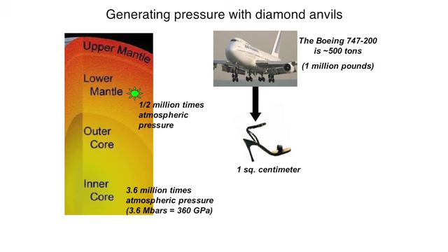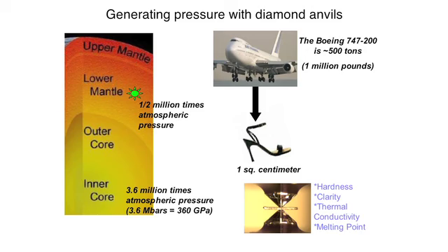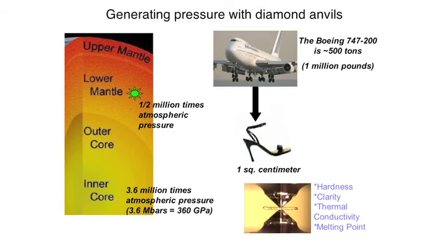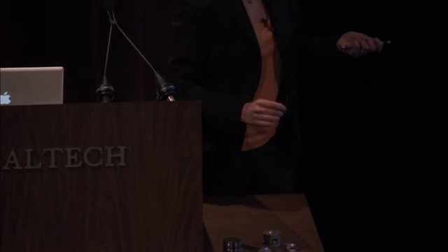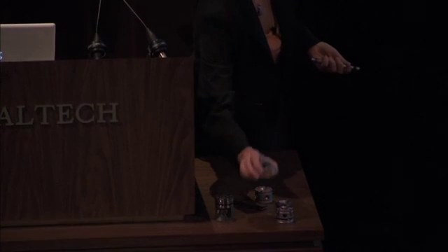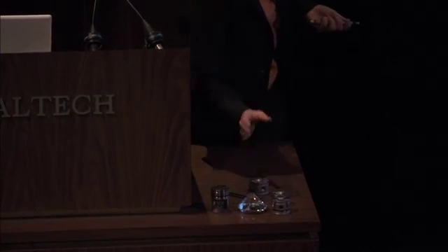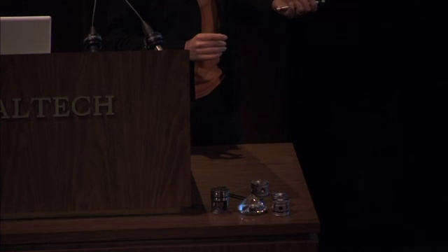So what we use is a diamond anvil cell. It's a small compact device. I brought several of them here, and different designs are used for different experimental probes. And okay, this is an enlarged anvil, of course, but we essentially take very small anvils, which are about 1/4 carat, and oppose them, cut off the culet, and place the sample on the culet with a metal belt around it. This is also called a gasket.